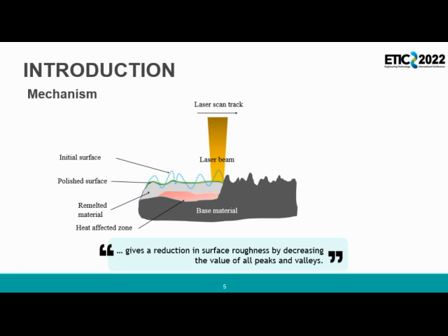In general, laser surface polishing gives a reduction in surface roughness by decreasing the value of all peaks and valleys. A number of process steps are executed, from macro polishing to increasing polish quality to smoothing out milling grooves. It is feasible to smooth out macro structures by utilizing laser light that emits a continuous wave.